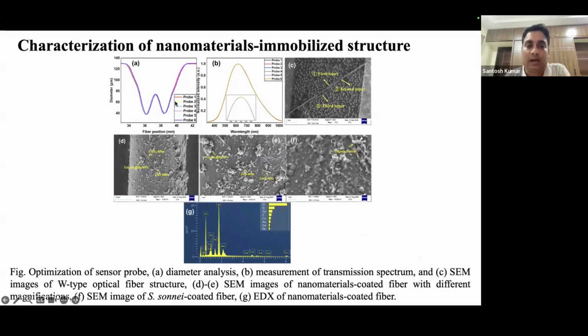So in this case, after the nanoparticle coating, this one is just a fabricated fiber structure, scanning the diameter of the probe, and the repeatability is quite high. We have also measured the normalized intensity through the developed sensor, and we found that the peak wavelength was the same. Okay, so after that this one is the original developed fiber structure.